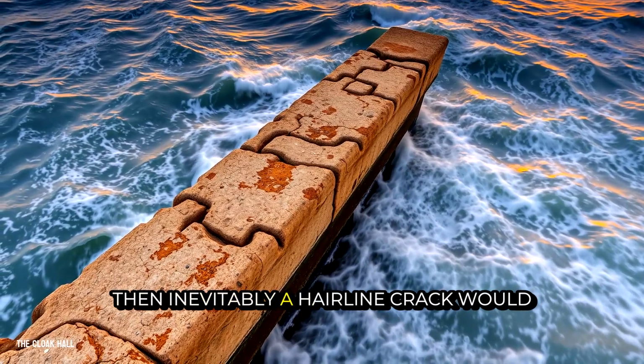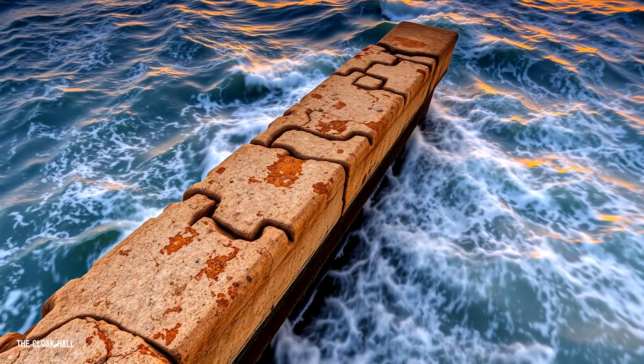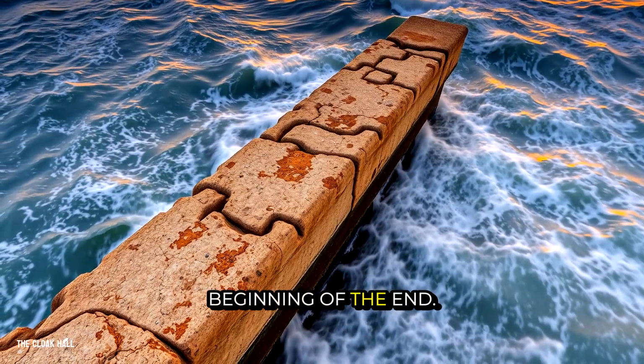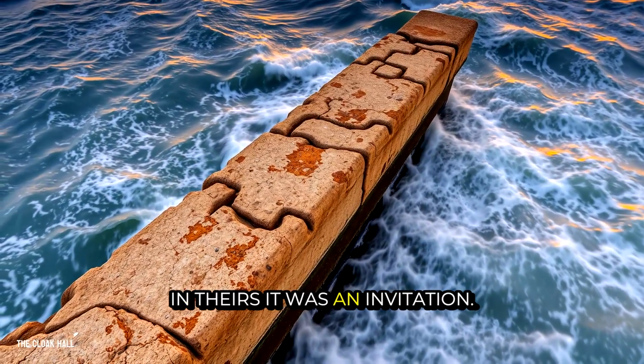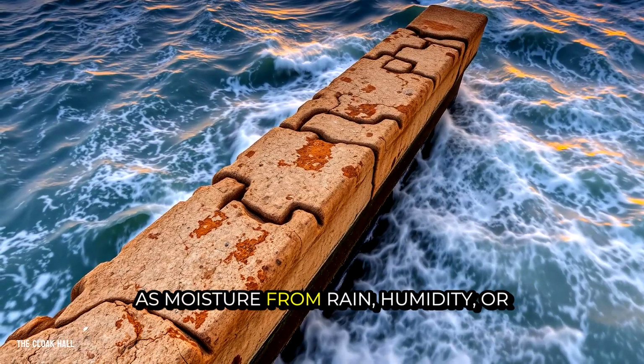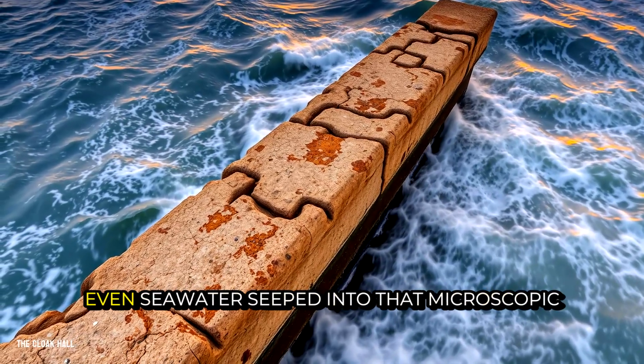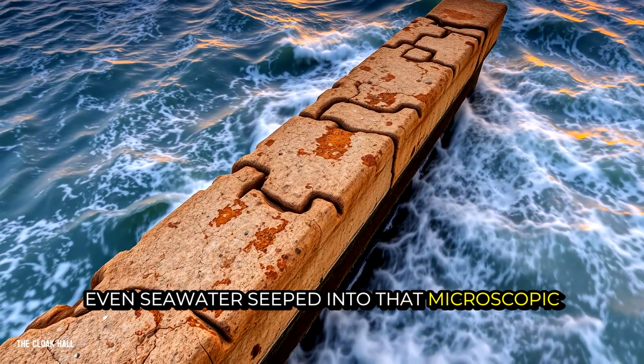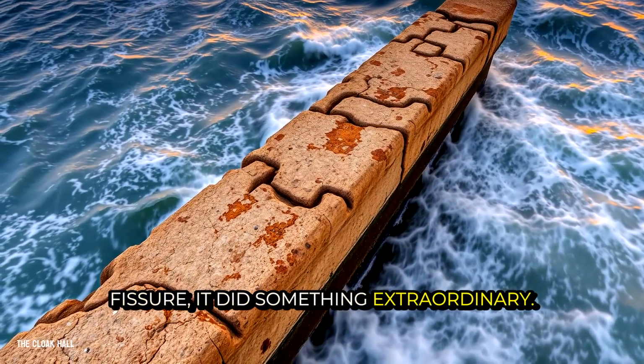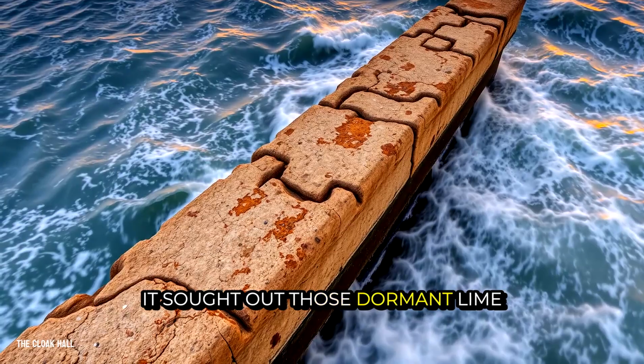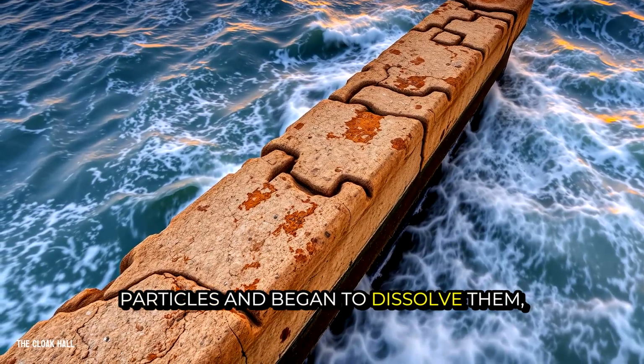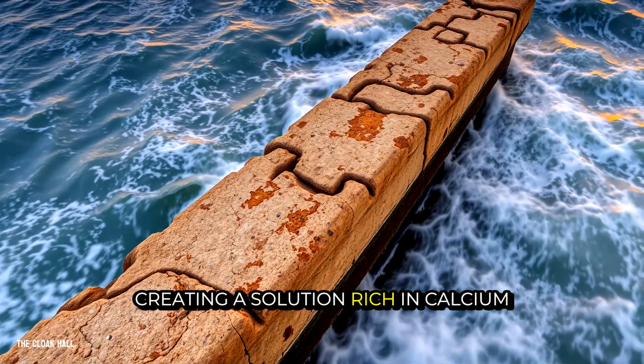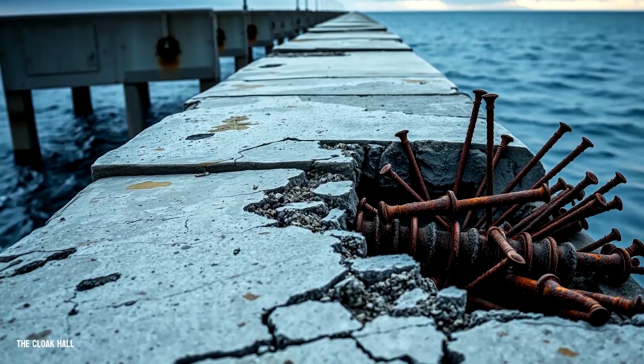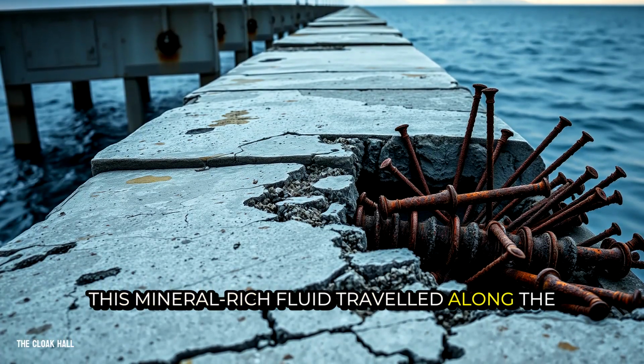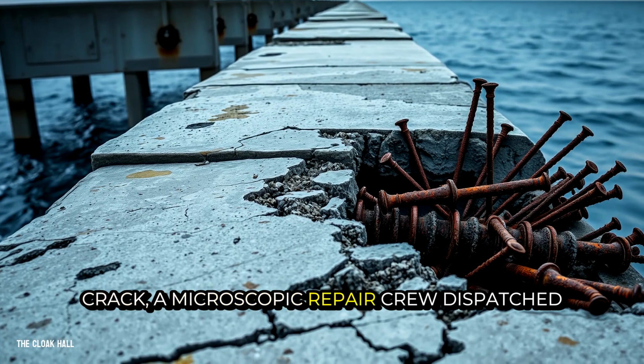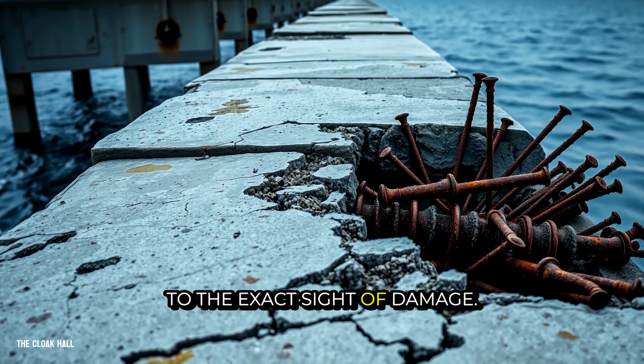Then, inevitably, a hairline crack would form. In our structures, this is the beginning of the end. In theirs, it was an invitation. As moisture from rain, humidity, or even seawater seeped into that microscopic fissure, it did something extraordinary. It sought out those dormant lime particles and began to dissolve them, creating a solution rich in calcium ions. This mineral-rich fluid traveled along the crack, a microscopic repair crew dispatched to the exact site of damage.